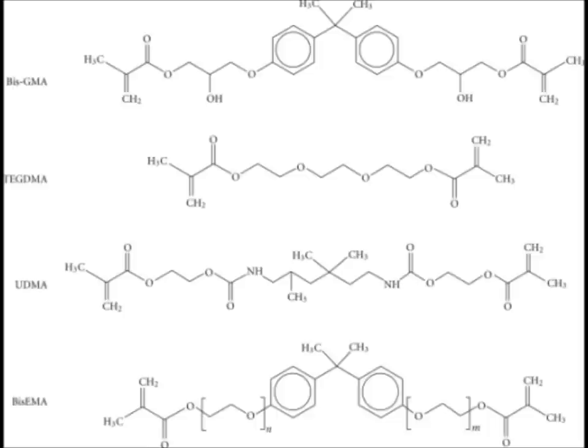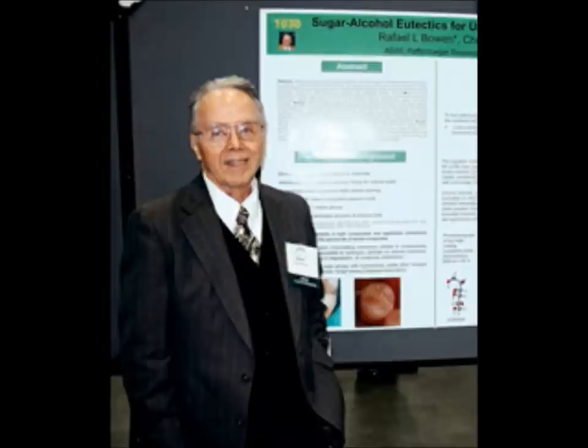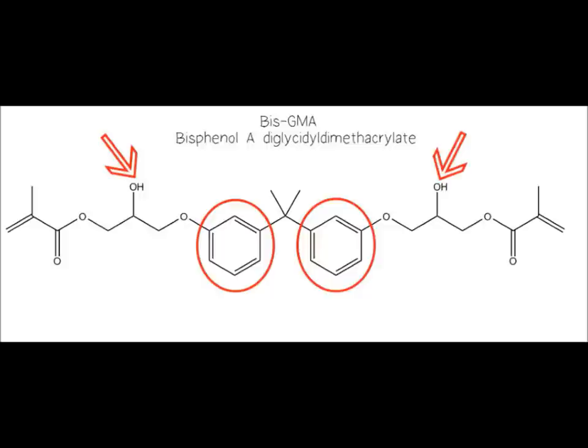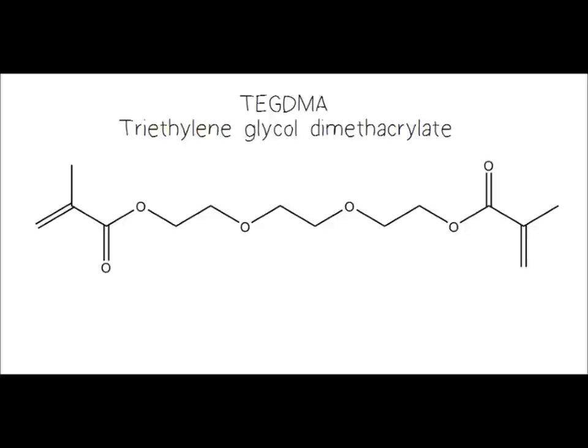During the manufacturing of dental composite, several different types of monomers are used to get the right consistency. The first monomer commonly used is bisphenol A diglycidyl dimethacrylate, or BisGMA for short, found by Bowen in the late 1950s. BisGMA is very viscous due to the presence of aromatic rings in the structure and hydrogen bonding on the hydroxyl group on the alkyl chain. This brings the structure close together, causing BisGMA to have low mobility and a higher glass transition temperature, or Tg — the temperature at which glass converts into rubber.